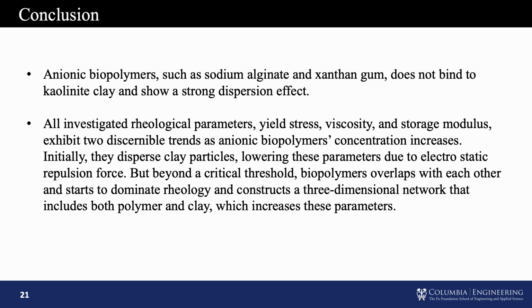In conclusion, all these anionic biopolymers we studied here, including xanthan gum and sodium alginate, and we also did some experiments on gum arabic, are all non-binding polymers that don't have a very strong binding affinity to the clay. And their rheology shows two distinctive trends. First, if you add a very small amount of polymer, it will disperse the clay particles and reduce the yield stress, reduce the viscosity, and reduce the storage modulus. And if you keep increasing the polymer concentration, the polymers start to overlap with each other to create a three-dimensional polymer network, which eventually increases the yield stress, viscosity, storage modulus, and the buildability of your material.